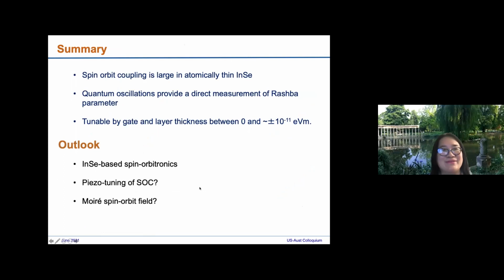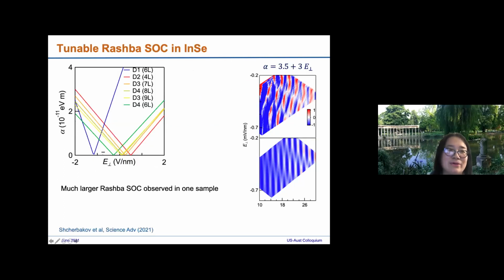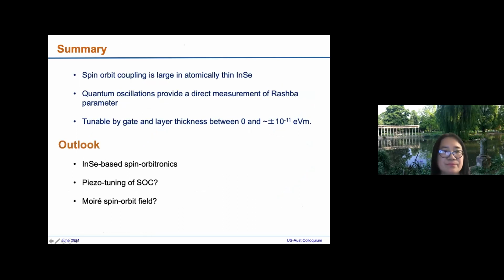So this is pretty much the end. Indium selenide is a really nice material. It can have high mobility, and the spin-orbit coupling is large and also tunable, so we can completely suppress it to 0, or we can make the spin splitting as large as 20-30 milli-electron volts by changing the electric field. So I think it is great for indium selenide based spin orbitronics. Of course, we can probably make Majoranas out of this too, because of this very tunable spin orbit Rashba, based on the proposals for coupling superconductors and spin orbit coupled materials.